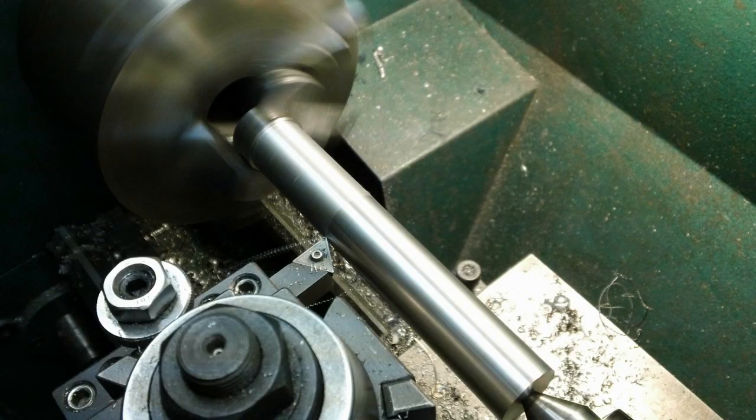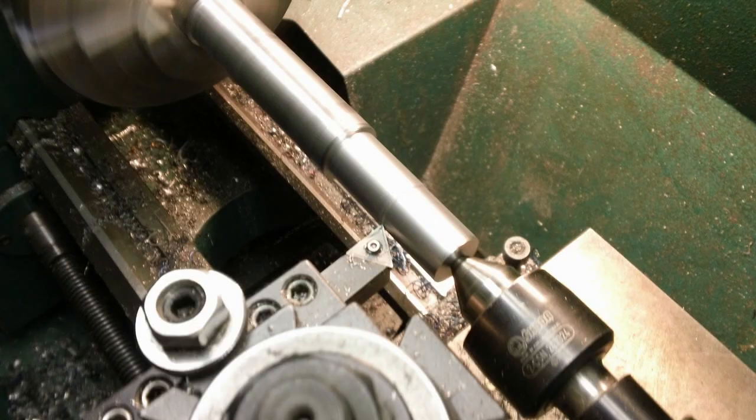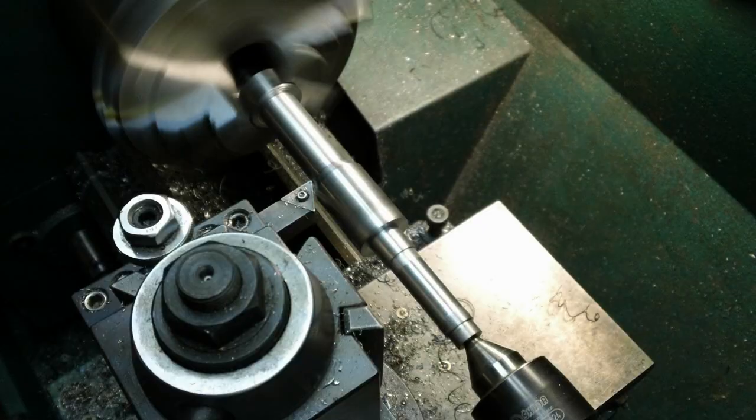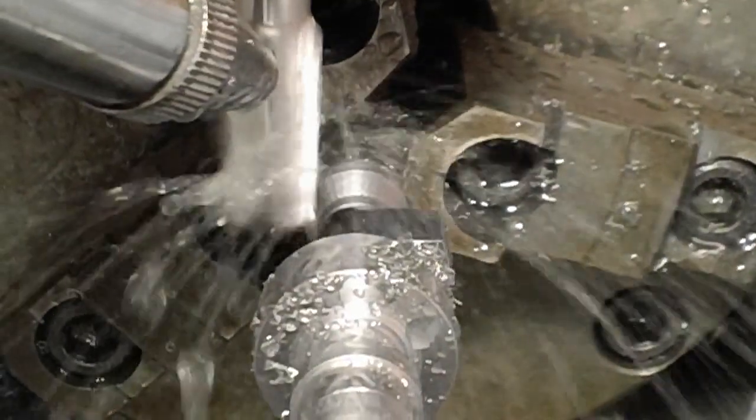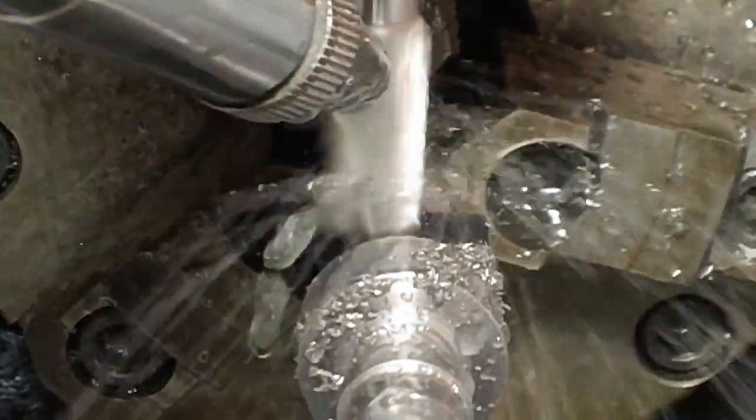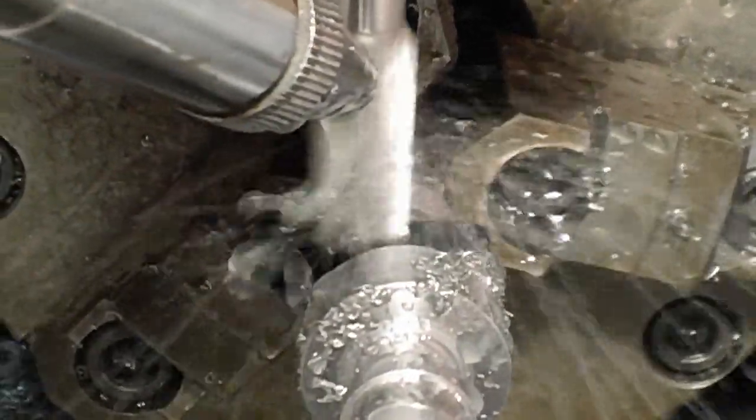The camshaft is made from oil hardened tool steel, a blank was turned on the lathe and the lobes were cut on the milling machine. A roller cam grind was extrapolated into a milling profile and then a milling bit was swiped across the cam blank at the extrapolated depth on 1 degree increments. A file removed the microscopic ridges.